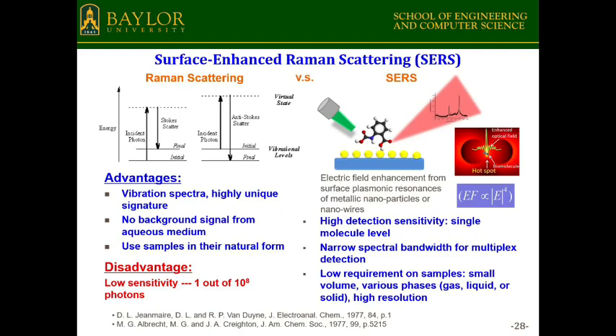But about 40 or 45 years ago, two scientists found that if you put the chemicals on a roughened metal surface, you can greatly enhance the Raman signal. Initially, they thought it was due to the enlarged surface area, but later on people discovered it is the surface plasmonic enhancement that increased the Raman sensitivity. The reason is that at the surface of the metal, the electric field is significantly enhanced, and the Raman sensitivity is proportional to the fourth power of the electric field.